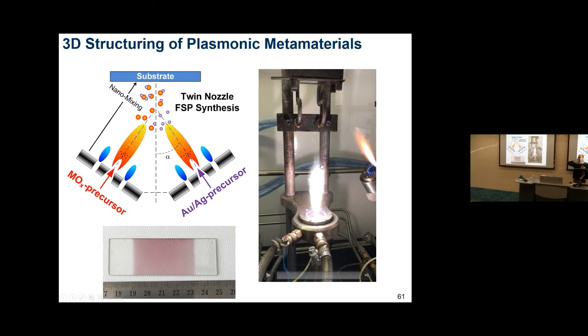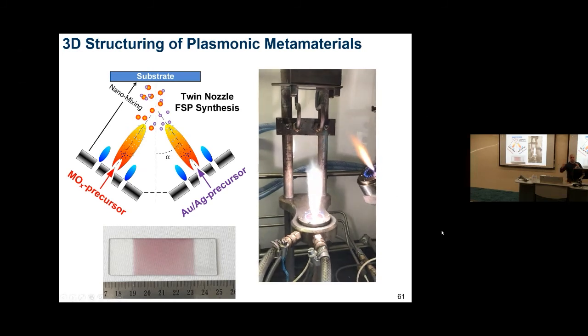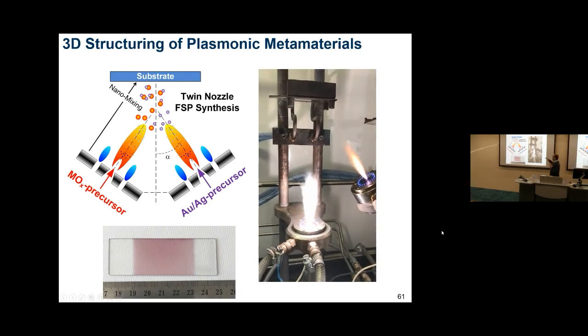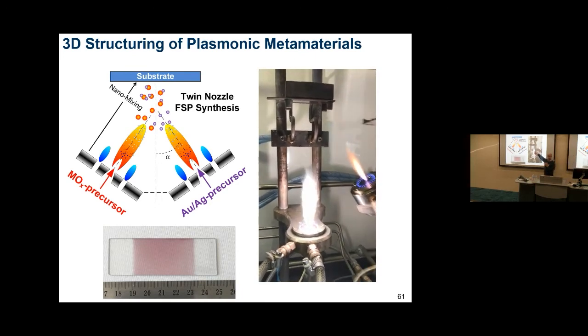Why should we have the gold on the bottom? We thought maybe we can actually deposit this gold nanoisland over the surface. What you see here is one flame producing titanium oxide nanoparticles and the other one producing gold, and they mix in the gas phase and deposit together.